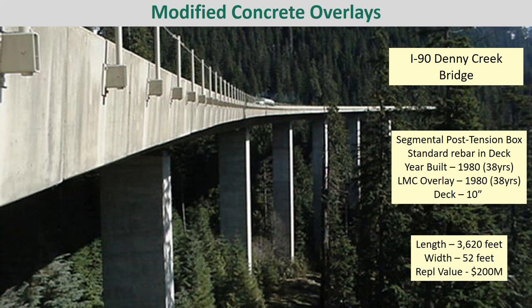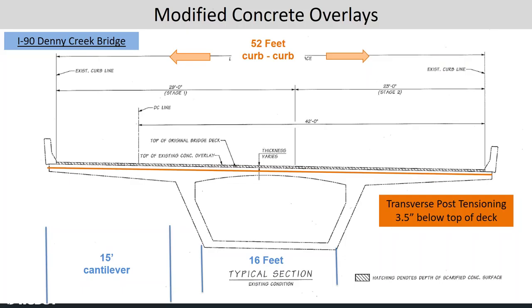Here's a unique bridge. If you've ever been up on I-90 coming westbound, this is the Denny Creek Bridge. It was the first segmental post-tension box girder bridge that we built in our state. Unfortunately, it was built prior to epoxy coated rebar, so it has standard rebar in the deck. And then it had an original LMC overlay that was put down in 1980. And then we recently rehabilitated this. The total bridge replacement value is about $200 million. So it's a very important bridge.